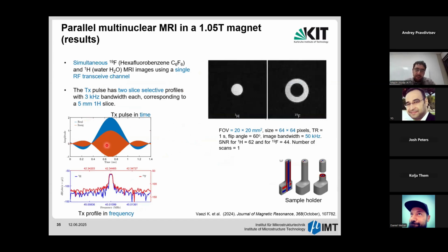Here's the excitation pulse in the time domain. In the frequency domain, it shows that it has two nice sharp excitation profiles at 42 and 45 megahertz with a bandwidth of 3 kilohertz. That's the slice thickness. The sample we used is a 3D printed sample holder with two chambers. One is filled with water, and the other one was filled with hexafluorobenzene as the sample for fluorine. And these two images are acquired simultaneously with a single RF channel.